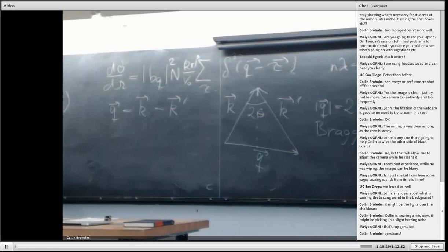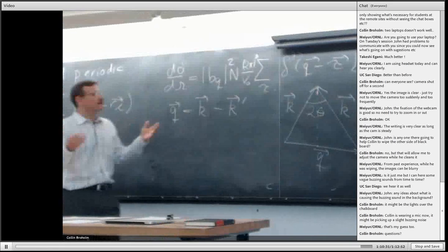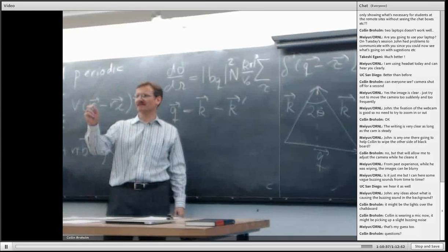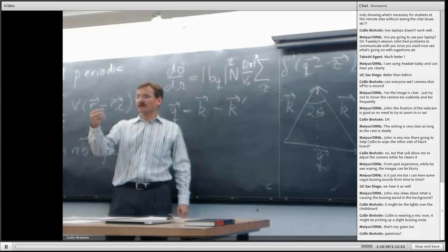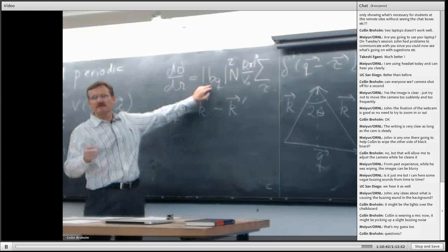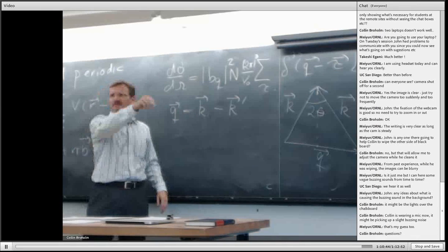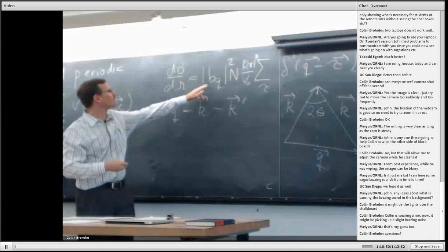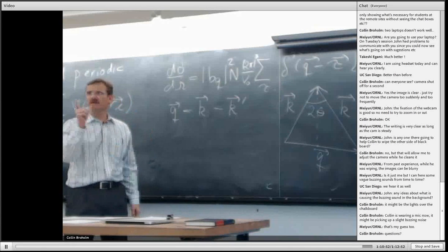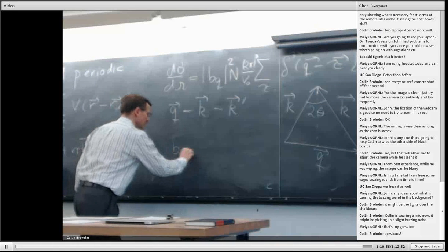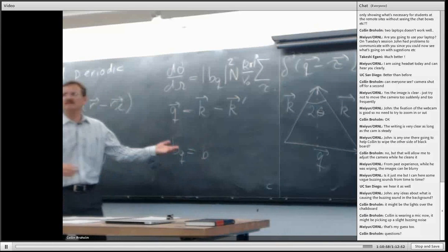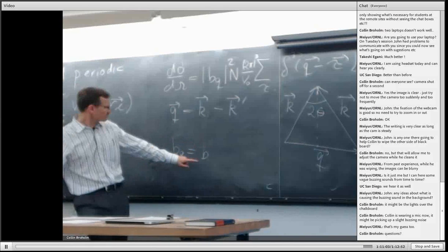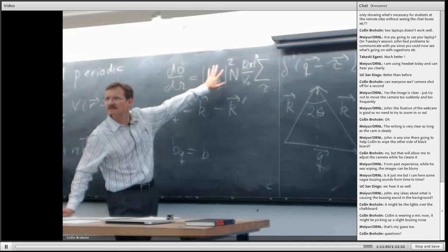And the zeroth order effect that you'll see show up is on the interaction potential, which we had postulated as being a delta function, right? We had this Fermi pseudo-potential, so that if I was in a situation of a Bravais lattice where there's just one nucleus per unit cell, then that nucleus has a delta function interaction potential, and the Fourier transform of that, in the case of just one nucleus per unit cell, B of Q, just becomes equal to the scattering length. So in that case, this is just essentially a constant.